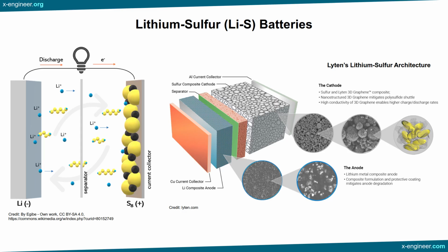Lyten has successfully manufactured lithium-sulfur batteries using existing lithium-ion production lines, achieving over 90% yield. Their process eliminates toxic solvents and reduces costs while maintaining compatibility with standard equipment. A sulfur cathode and lithium metal anode have the potential to hold multiple times the energy density of current lithium-ion batteries. Lyten uses that potential to build a practical battery without heavy minerals like nickel, cobalt, graphite, or iron and phosphorus. The result is an up to 50% weight reduction versus NMC and up to 75% weight reduction versus LFP.